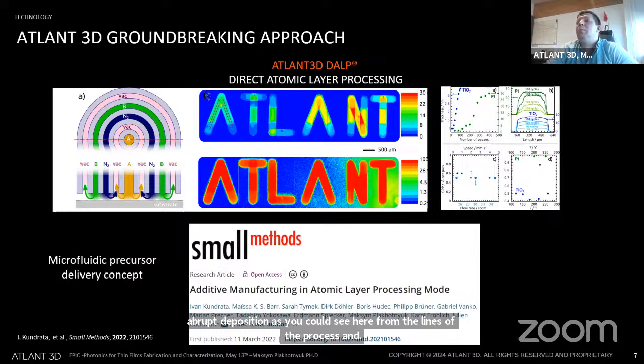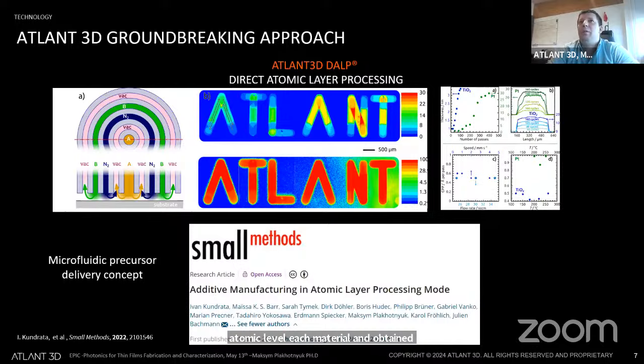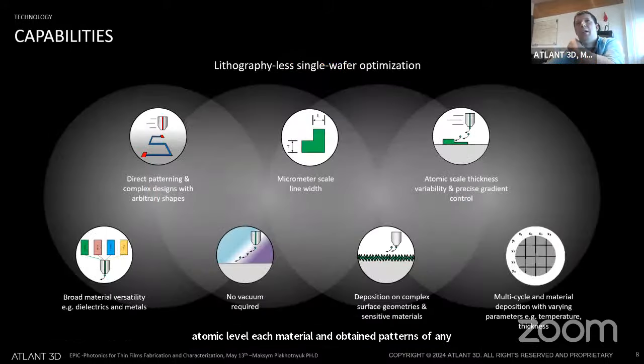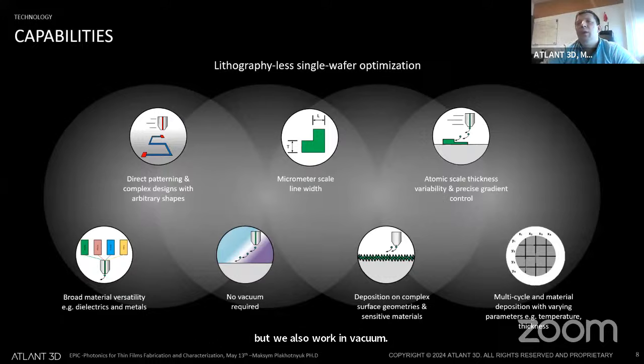And this basically gave us a possibility to control at atomic level each material and obtain patterns of any shape. So today the technology has several critical capabilities of direct patterning, local deposition, broad selection of material. It doesn't require vacuum, but we also work in vacuum. Micrometer scale line width. We recently demonstrated few micrometer line width. Since it's ALD, it can work on very complex surfaces, not only flat wafers, but membranes and nanostructures. And it allows also processing across the whole value chain, from material processing to scalable manufacturing.